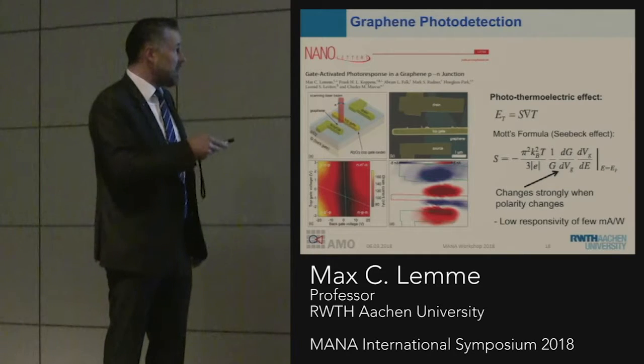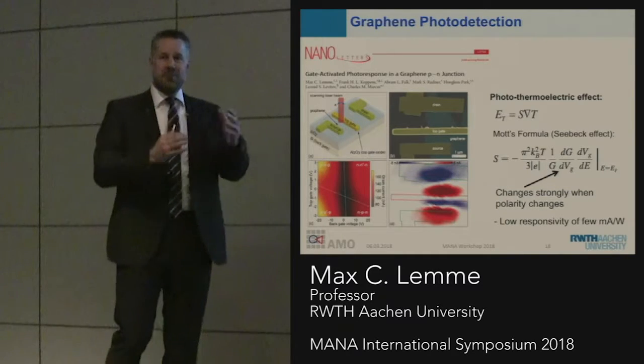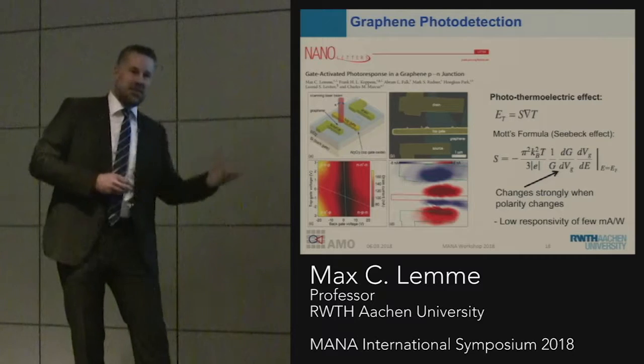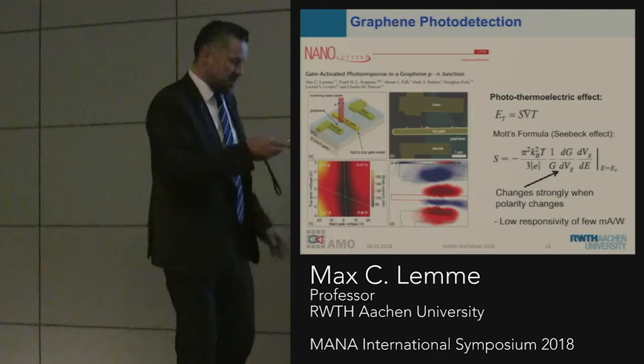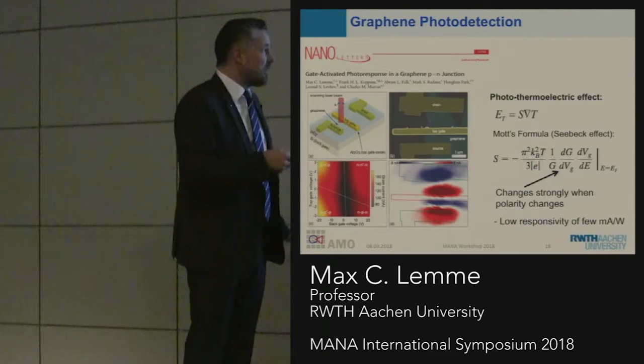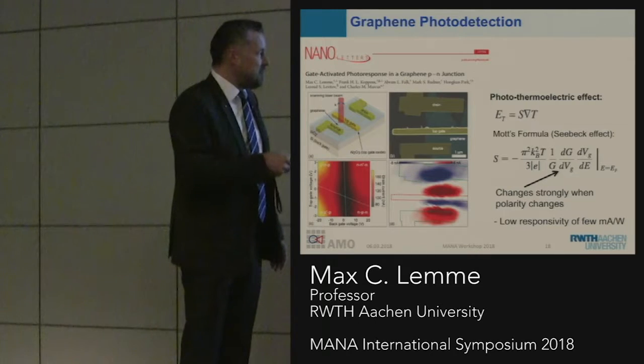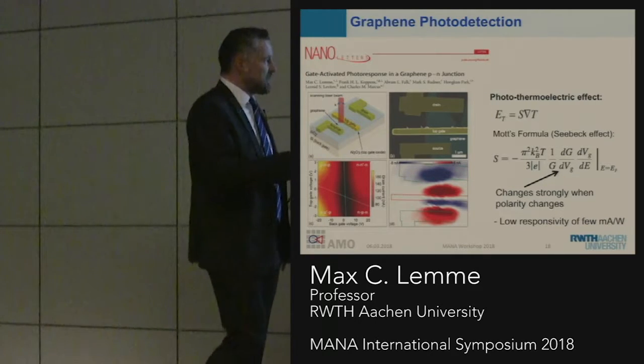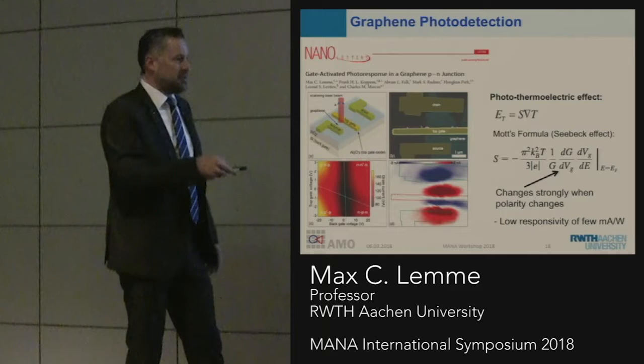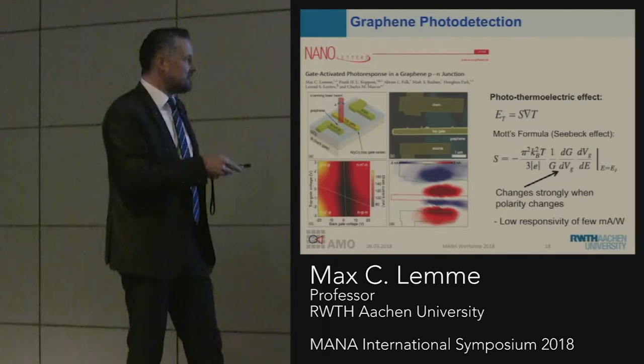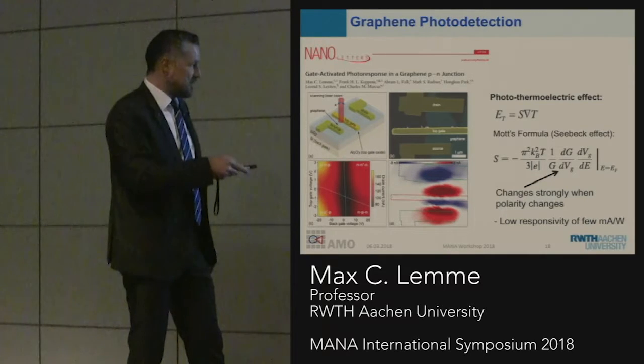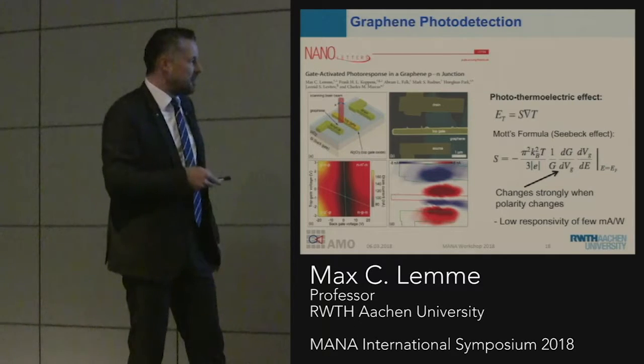It turns out it was close to the contacts and close to the gates. By changing the back gate and the top gate, you can play around with the carrier density in the graphene and the carrier type. At the end of the day, we established that probably it's a photothermoelectric effect, where the Seebeck effect comes in, because that changes strongly when you change the polarity. So when you have a PN junction in the graphene near the top gate contacts, you get a strong photocurrent.